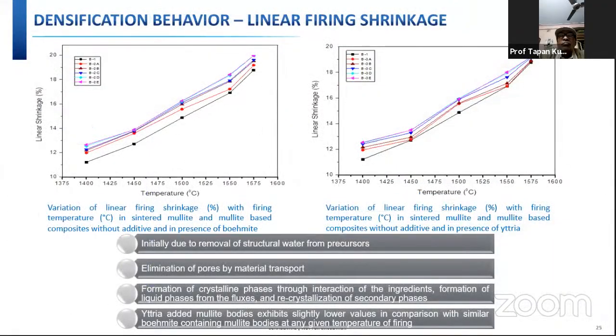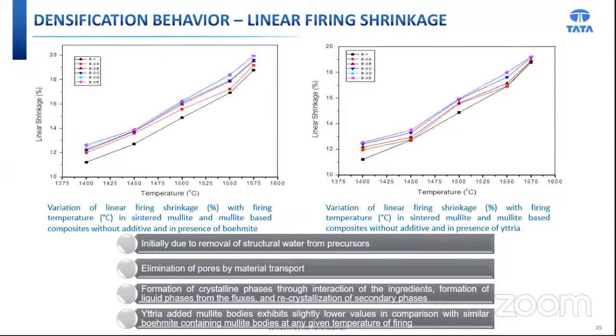Now coming to the linear firing shrinkage. This is the densification behavior. Basically, the shrinkage of such a multi-phase precursor is initially due to the removal of structural water from the precursor, elimination of pores by material transport, the formation of crystalline phases through the interaction of the ingredients, formation of liquid phases from the fluxes, and recrystallization of secondary phases.